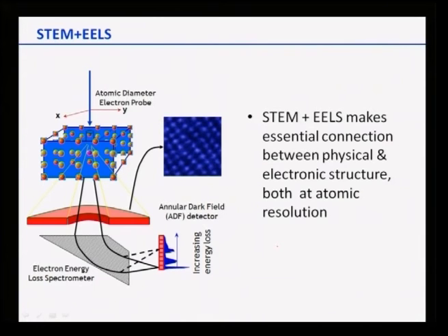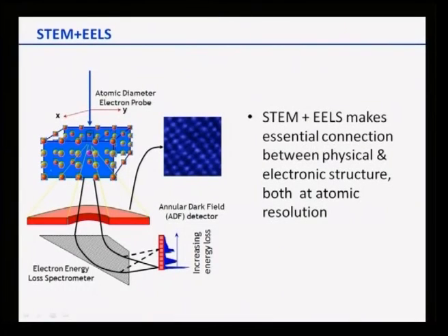The last thing which I am going to show you is called STEM+EELS. STEM+EELS in the sense that it can be used to determine the particular atom present in a high resolution microscopy image. Let me tell you what is done. Suppose this is the atomic arrangement of a certain compound, with different colored atoms. You have an electron falling onto that, and each atom has a different scattering power, right. That depends on the atomic electronic configurations. So depending on the scattering power, electrons get scattered at different angles.